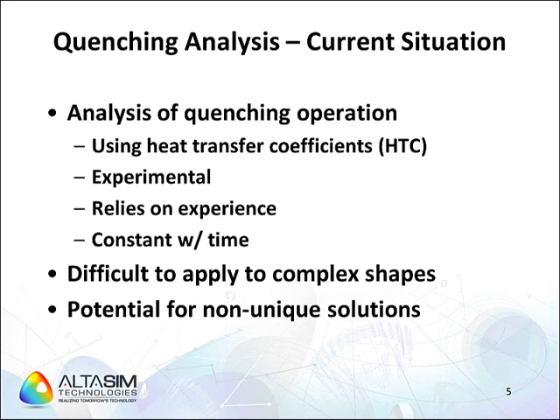This assumption can produce inaccuracies across the solution as the cooling varies with temperature of the part. Additional difficulties arise with HTCs developed for simple geometries as they are applied to complex shapes. These experimentally determined HTC values may not represent the cooling experienced by the actual part being quenched. Finally, the method used to develop these HTCs from experimental data can develop non-unique solutions that correlate with experiments and yet fail to operate successfully in the analysis of complex parts.